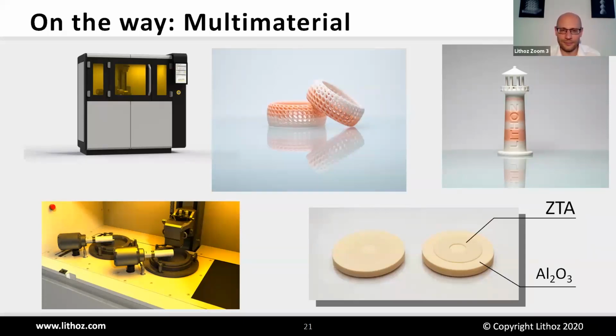Davide seems to have some issues, so I'll just follow up on his questions, or Isabel can take over. There is a question: I wish to know the sintering time required for a cubical component of 10 cubic centimeters. Basically, sintering takes a couple of hours to a day. It's not really dependent on how big the part is, but how much you put into the furnace. But this is not really an issue. The more critical time is the debinding time. I think I need to speed up a little bit.